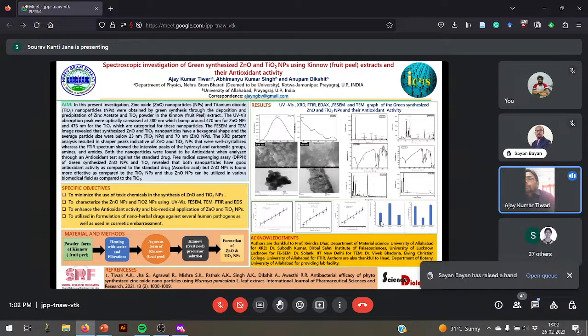Both the nanoparticles were found to be antioxidant when analyzed through the antioxidant test against the standard drug, free radical scavenging assay DPPH. The green synthesized zinc oxide nanoparticle and titanium dioxide nanoparticle reveal that both nanoparticles have good antioxidant activity as compared to the standard drug, ascorbic acid. As a standard drug, I have taken ascorbic acid. But the zinc oxide nanoparticle is found more effective as compared to the titanium dioxide nanoparticle, and thus zinc oxide nanoparticle can be utilized in various biomedical fields as compared to the titanium dioxide nanoparticle.